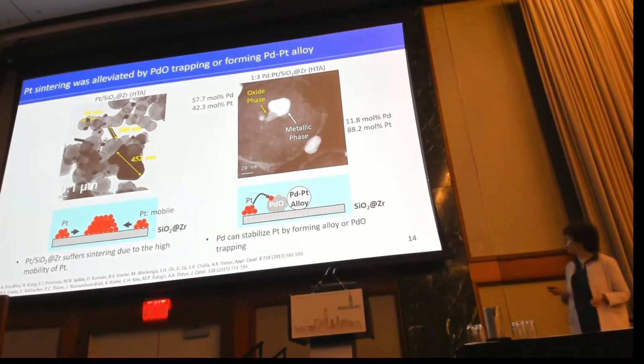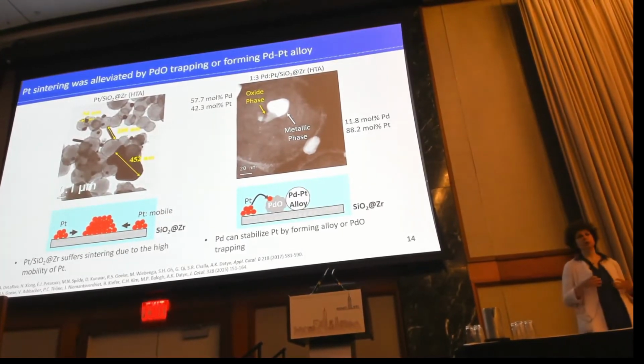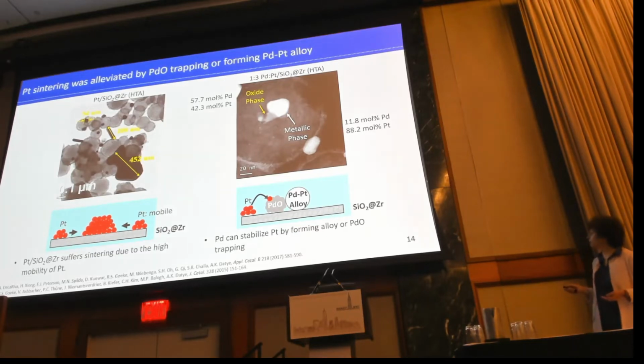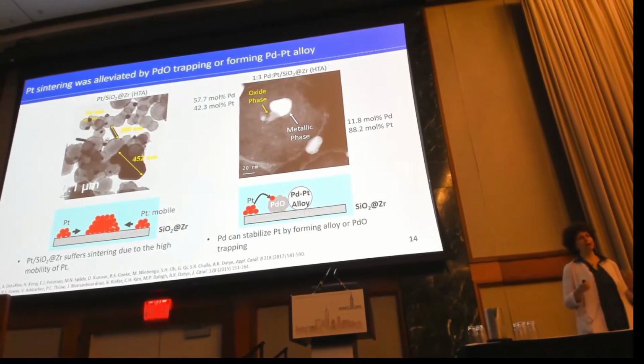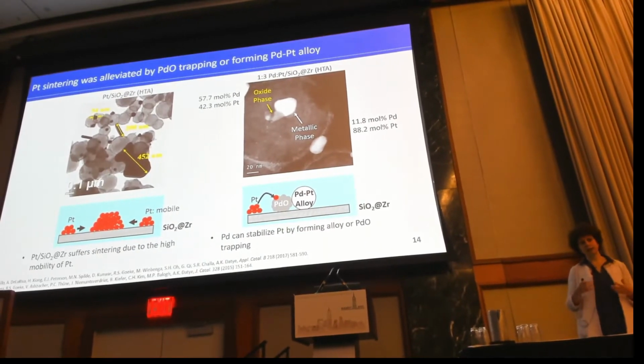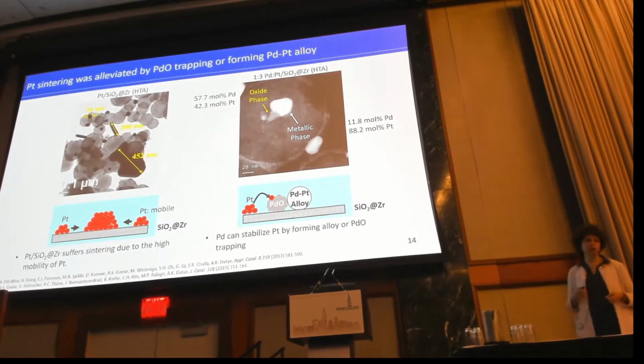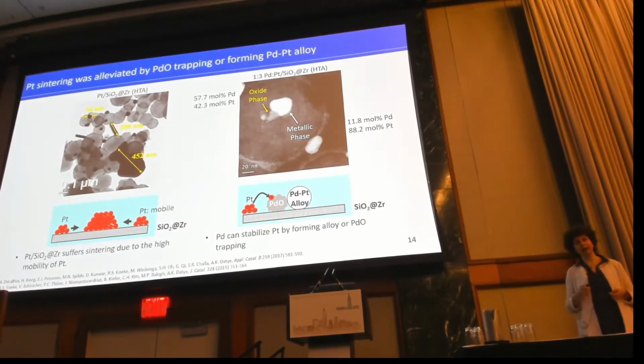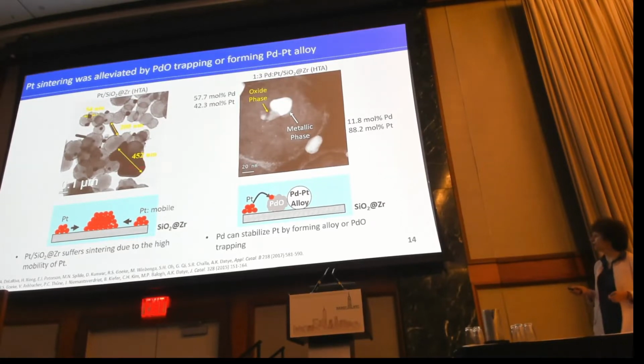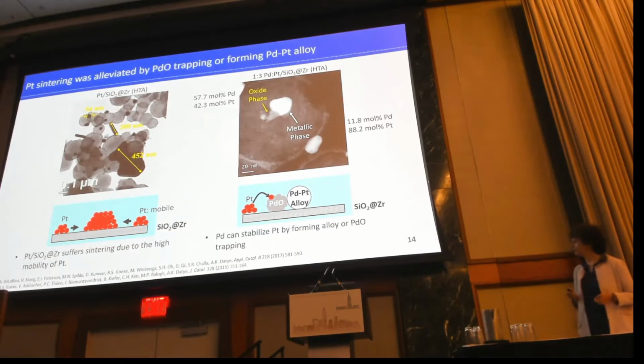So what we think is happening here is that, again, platinum is mobile during hydrothermal aging. It can form alloys with palladium, but it can also be trapped by the palladium oxide phase. And this is a mechanism by which the platinum is becoming stabilized in the bimetallic catalyst. And that's why we don't see the big platinum aggregates that we saw in the monometallic platinum catalyst.